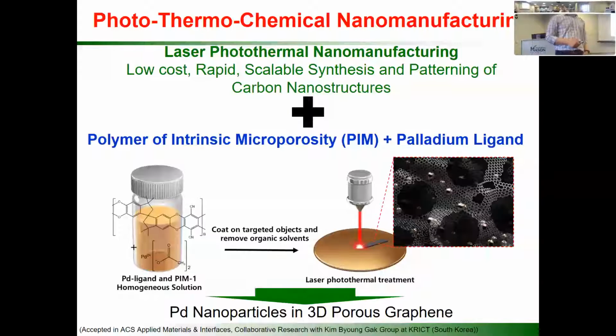So we started to manufacture this material using lasers. As I mentioned, we use CVD to synthesize the graphene material. But now the mechanism is the same. We shine a very strong light onto the polymer, so now we use the polymer as a precursor. Before, we used methane to get the carbons, but now we use the polymer, and then we shine the light, and they locally increase the temperature to over 1,000. That's the way we can fabricate the material in less than a second, on the order of microseconds actually.